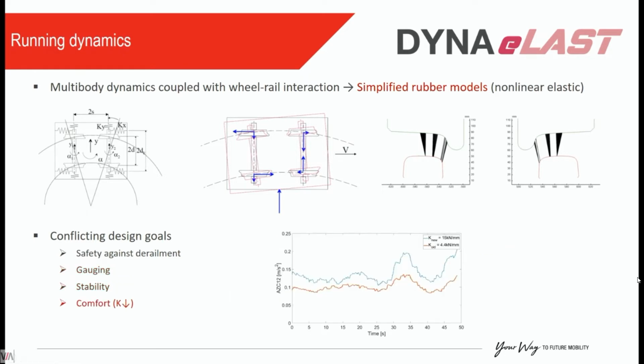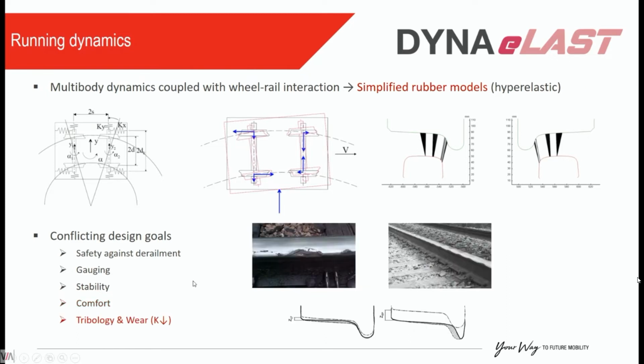When it comes to comfort, here you can have different circumstances, but for example, in this particular case where we tested bushes of different stiffnesses, this is vertical acceleration experienced by the passenger. We see that a stiffer suspension, a stiffer bush, leads to higher acceleration, which is less comfortable. So in this particular case, we needed to use the stiffer suspension, but it was a trade-off because we were aware that we were worsening the comfort characteristics.